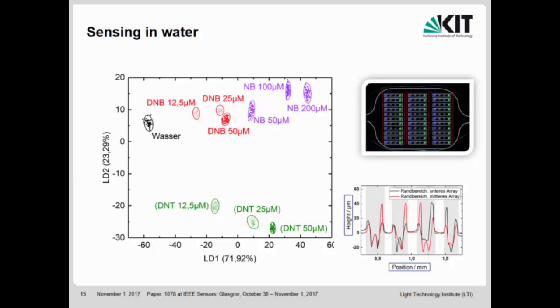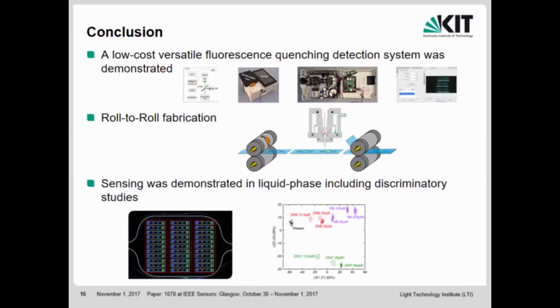So if we take them out of the analysis, then we could end up with a discrimination that has a probability of more than 95%. Even though they are close together, if you observe them in a three-dimensional space, you would see that there are different branches going up and down. So, to conclude, I introduced a relatively portable system that is able to detect fluorescence quenching. I showed you the manufacturing scheme, which enables roll-to-roll fabrication in the future. And we could also prove that these more or less first arrays are able to discriminate these different concentrations.